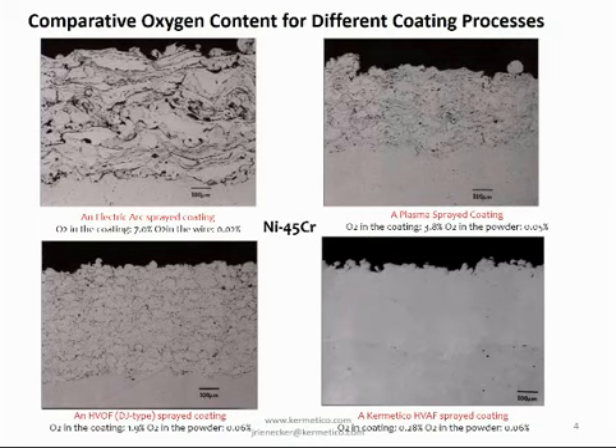Then we have a DJ coating, same type, HVOF: 0.06% oxygen in the powder, but only 1.9% in the coating. Again, that is apparent from looking at the comparison in the photomicrographs between plasma and HVOF.